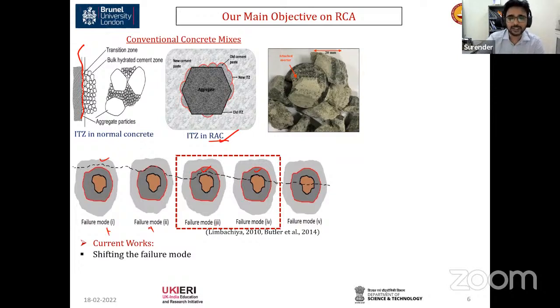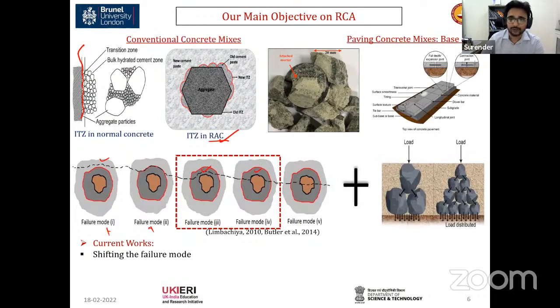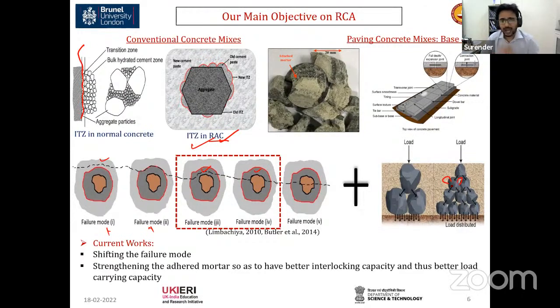If I talk about special kinds of concrete, let's say pavements or roller compacted concrete, apart from the interfacial transition zone, the load carrying capacity of those mixes also depends upon the aggregate to aggregate interlocking. So if you are using recycled concrete aggregate that has adhered mortar content, the aggregate to aggregate interlocking capacity will be affected, right? So we are also exploring how to enhance, like Rohit has mentioned, how to remove the adhered mortar, right? But if you want to use it in as-received state, then we need to enhance the bonding between the old mortar and the aggregate, or we need to address the issues with the old mortar. So right now we are also working on strengthening the adhered mortar so as to have better interlocking capacity and thus better load carrying capacity of the mixes.